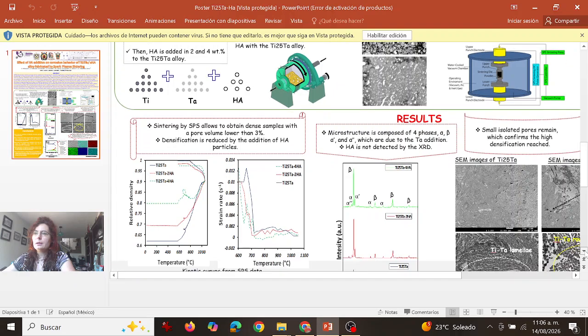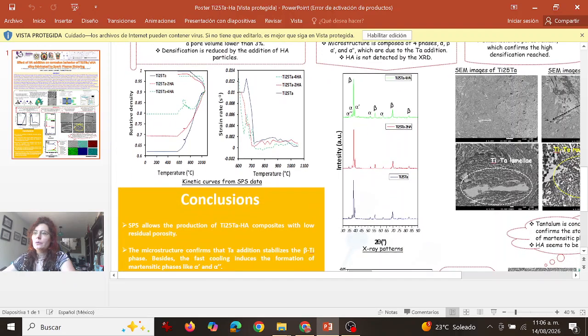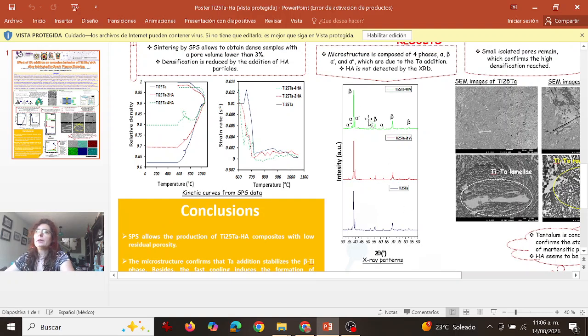With the results that we obtain from the X-ray diffractometer, we can have a look at the X-ray patterns. Basically, what we can see, especially in here, is that the microstructure is composed of 4 phases. Here we can see these 4 phases.